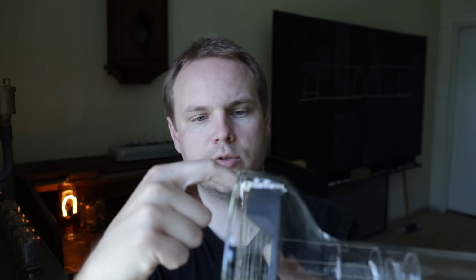So let's have a closer look at the second problem, the dynode oxidation. The source of the problem is the process when we seal the front window to the main envelope, because we need to increase the temperature on the edge to something like 1000 degrees Celsius. And if there is any oxygen inside the tube, it will react with the stainless steel dynodes and turn them brown or yellow.